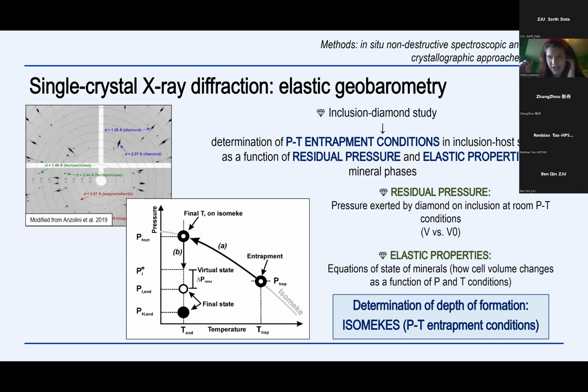And now we can start with the most interesting part of this presentation, the data and the results that I obtained during my PhD. I want to start with the first example, which summarizes the results recently published in Geology, in a work titled "Ringwoodite and Zirconia inclusions indicate downward travel of super deep diamonds." This study is extremely important because it determined for the first time that diamonds, after their formation in the Earth's mantle, can also travel downward toward higher pressure, and not only upward toward the surface as was commonly assumed before this study.